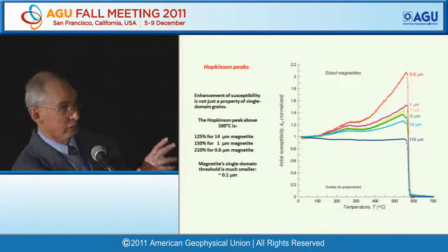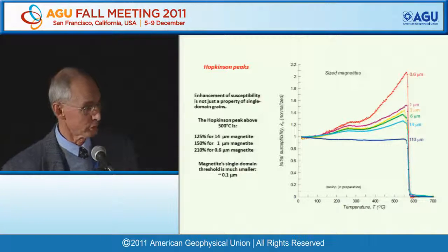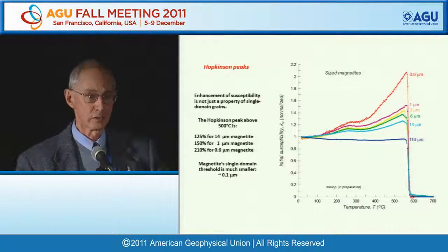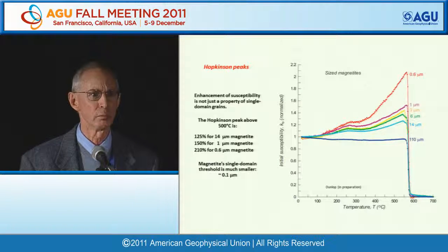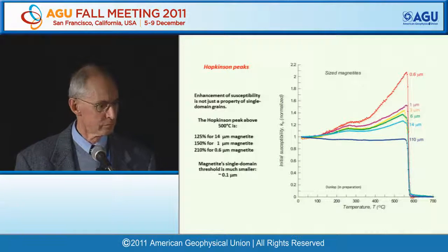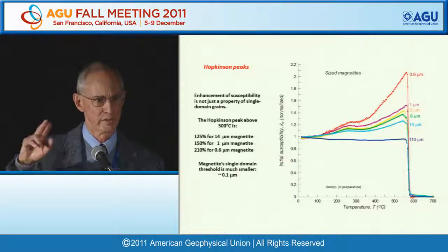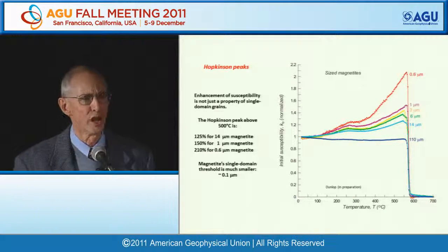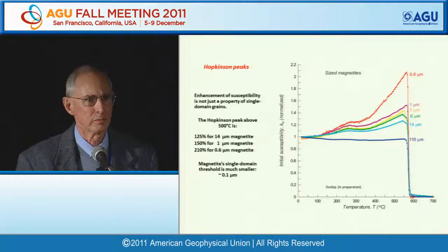So the answer is, when you go to larger grain sizes, you get the multi-domain flat plateau. So the first evidence of any sort of peak is around 14 microns.